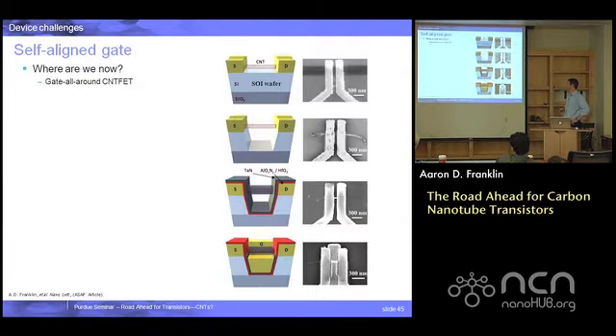And this is the process flow for it. It's so new, I actually show some of the experimental details here instead of skipping over it. One of the hard things with nanotubes is you can't put them in a reactive ion environment, really virtually any, or they will etch. They're very reactive, being all on their surface and having their bonds sort of stretched tight with rolling them into the cylinders. They are reactive to virtually any species. So if I want to etch something anisotropic, it becomes a real challenge.